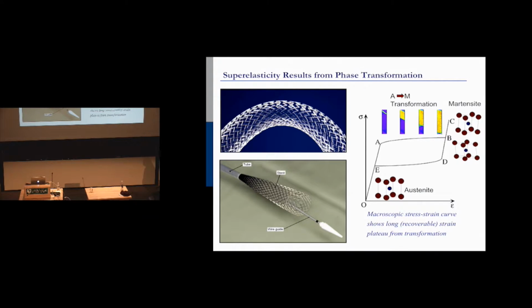This is cubic. That's monoclinic. Okay, some variant of the martensite. There's actually 12 variants of monoclinic that are energetically the same. Okay? And it propagates through until you're here. And then you're basically elastically loading the austenite.